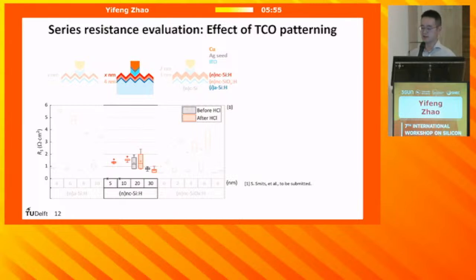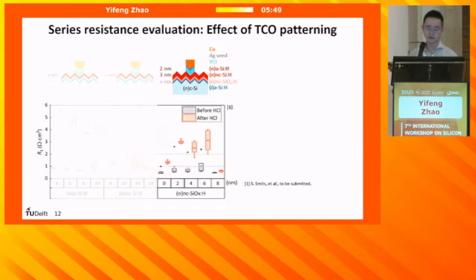However, if the nanocrystalline silicon layer is too thick, that can also make later patterning of this silicon layer a bit more challenging. Further on, we combined our optimized bilayer stack with an N-type nanocrystalline silicon oxide layer. As you can see, with a thickness of 8 nanometers, we can control the device series resistance consistently below 1 ohm square centimeter, even after patterning the TCO.